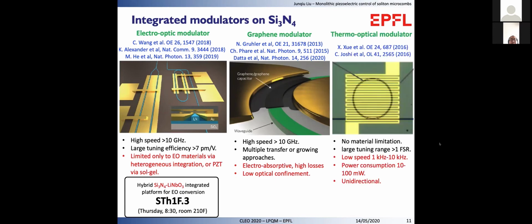The third scheme relies on thermal heaters, which can work on a variety of materials. It enables a large tuning range of 1 microresonator FSR. However, heaters are slow, with actuation bandwidth typically between 1 kHz to 10 kHz. Also, it continuously consumes high power, around 100 milliwatts. Third, it enables only one directional tuning, as heating the chip is much easier than cooling the chip with current.